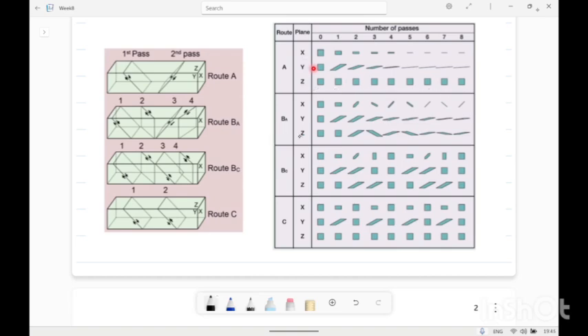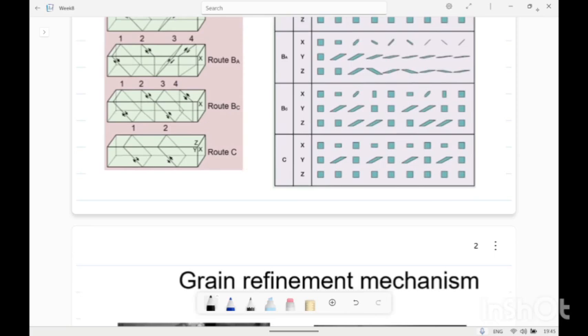In route A, no rotation will be done, meaning the same pressed part will feed into the next pass in the same direction. In route BA, the 90 degree rotation with alternate direction leads to different orientation of slip planes and deformed regions. Similarly for BC, the deformation orientation is different.